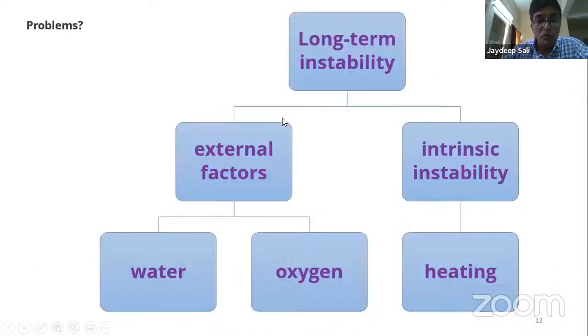According to the International Electrotechnical Commission's standards, a solar cell must perform under non-laboratory conditions such as damp conditions, 85% humidity at 85 degrees Celsius, and they must withstand such harsh conditions for more than 1,000 hours consistently. But here the perovskite material fails. So in order to enter the current market, the durability of perovskite solar cells must be improved, and most of the present research efforts are focused towards the stability of the perovskite material.